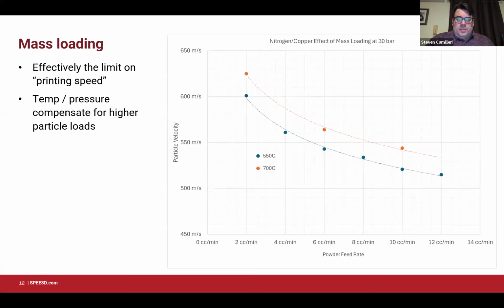So here we have a little bit of discussion on mass loading. This is just holding 30 bar and trying two different temperatures. So we've put in the copper particles and we've changed the mass rate at which we're feeding those particles. That's what's on the x-axis down there. Different mass rates, and the two lines each represent a different operating temperature. And you'll see that as we increase the mass loading, so that we inject more and more powder into the nozzle, the particle groupings are slowing down in velocity. This is what we expect, but it was great to be able to map out precisely how that works.